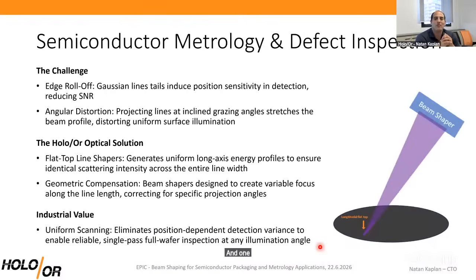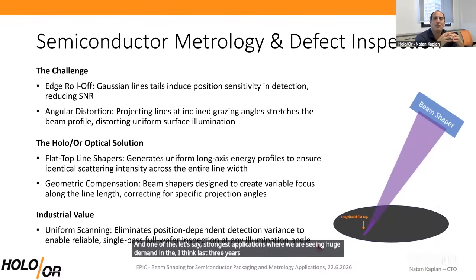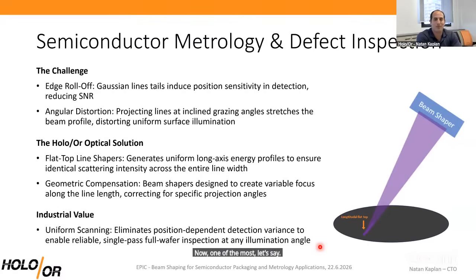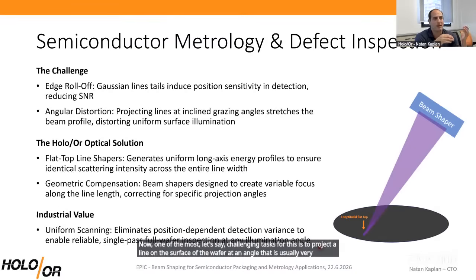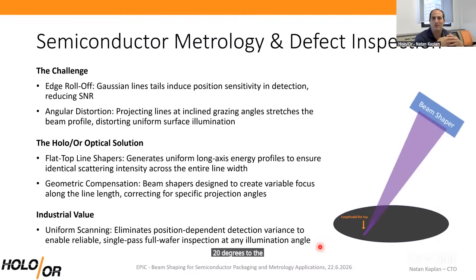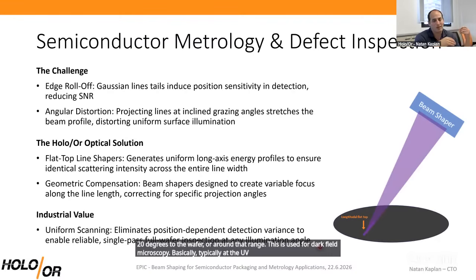And one of the strongest applications where we are seeing huge demand in the last 3 years is wafer metrology, especially bare wafer metrology before processing to evaluate various defects, but of course also metrology when there are devices. Now, one of the most challenging tasks for this is to project a line on the surface of the wafer at an angle that is usually very grazing. It's something like 20 degrees to the wafer or around that range. This is used for dark field microscopy, basically, typically at the UV wavelengths. And this is one of the best ways to detect very small defects using a laser light.